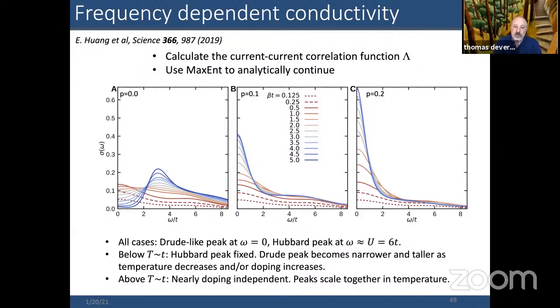But as soon as one dopes, you can see you get a Drude peak that appears at low frequencies, and that Drude peak continues to grow as you come down in temperature, and its width seems to be a little bit narrower as you go from 10% to 20%. And if you look at the high frequency end, or at temperatures on the order of t or greater, it's largely doping independent. And in fact, the peaks scale together in temperature at these values.